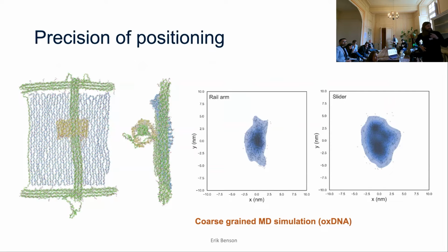So we can try to use simulation to get a feeling of how much the slider is moving on top of the rail arm. This is just a nanometer scale. You have a motion along this axis that's on the order of 10 nanometers, and around 5 nanometers of motion in this axis. So I think it's pretty obvious that we need to improve the fit of this device, get tighter fits of all the components, and we can get less flexibility in the system.